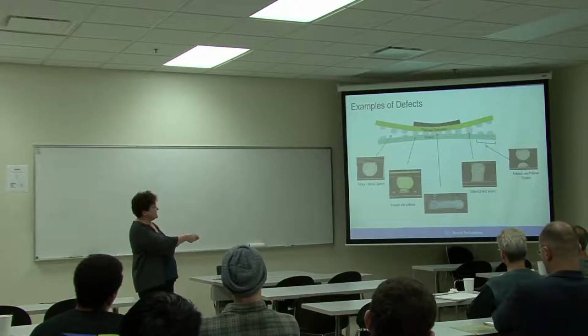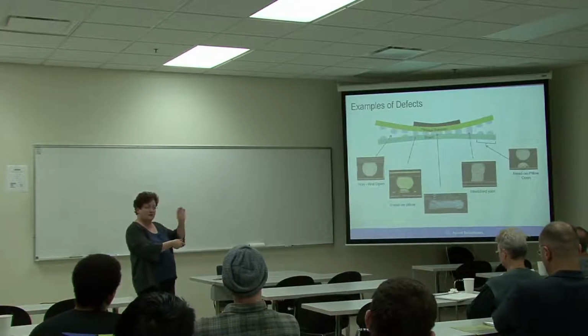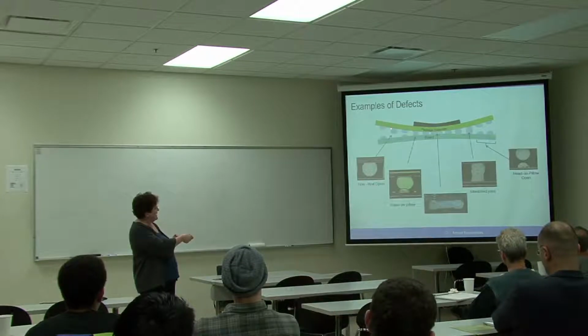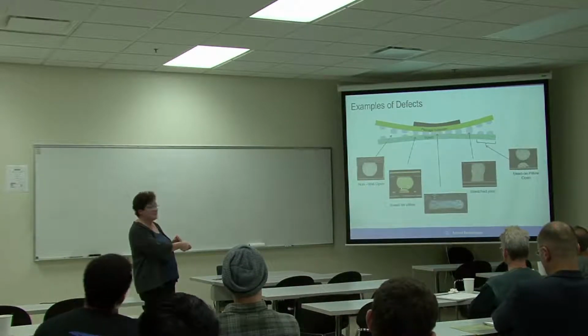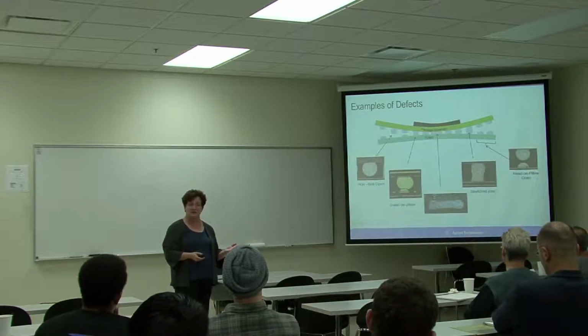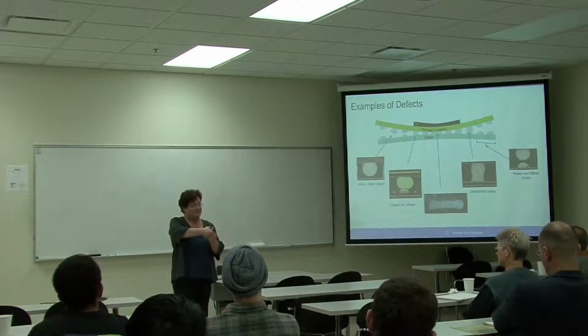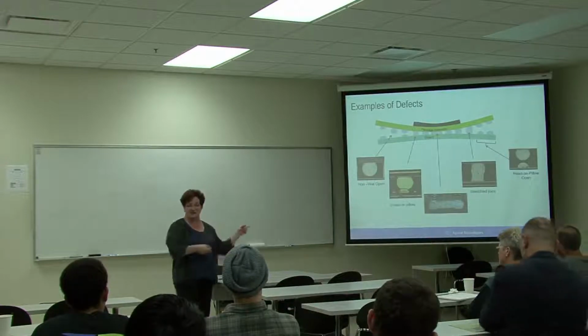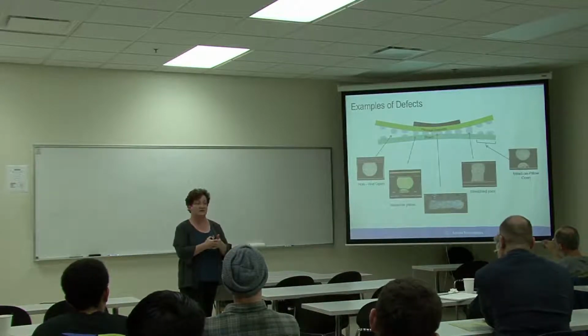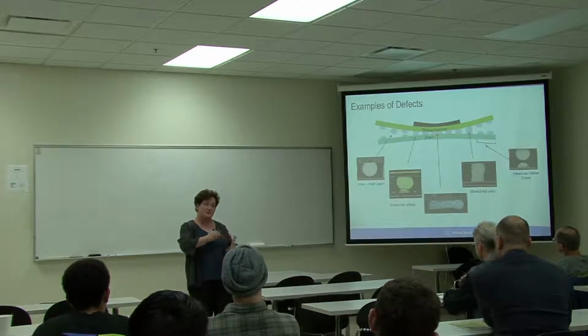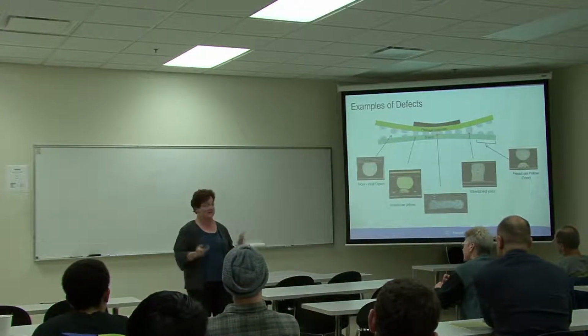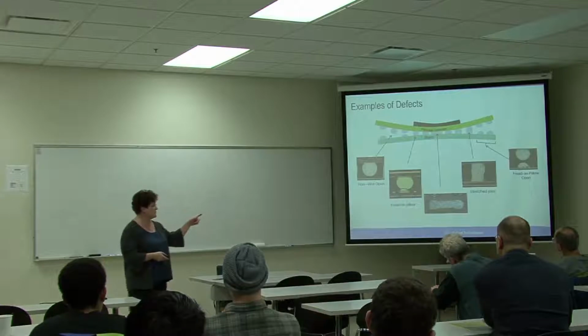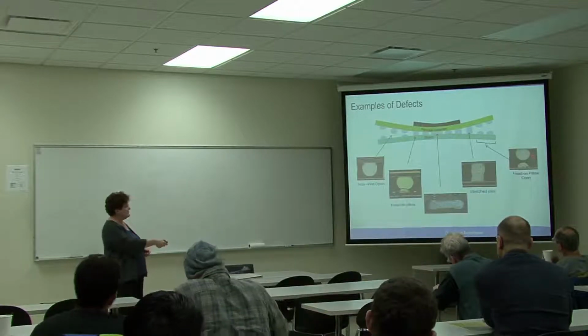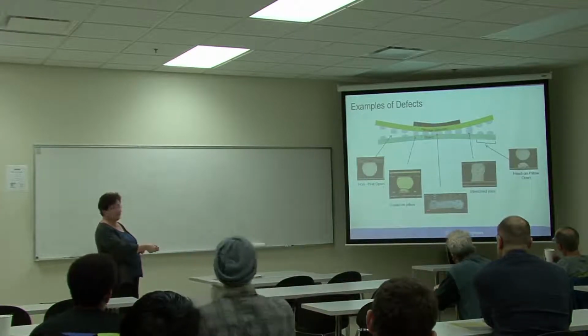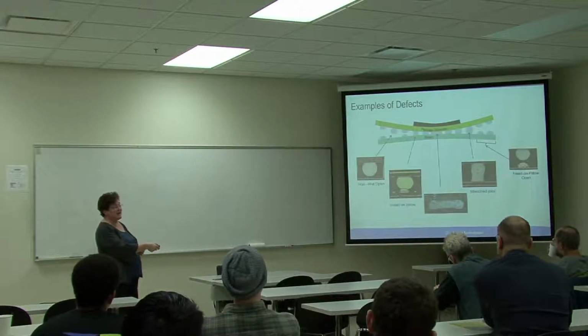This is a representation of what's called a ball grid array, so it's balls of solder attached to the part, and this ball did not actually wet to the paste, and so that means that you don't have a metallurgical joint, you just have a physical connection, and those are the absolute worst kind of things to have, because what happens is they're connected now, and a few thermal cycles, on-off cycles later, it disconnects, and so it fails in the field. So those are the sorts of things we really want to avoid. Something like this, we'll find right away. Something like that, we'll find right away. This one might have a short life.